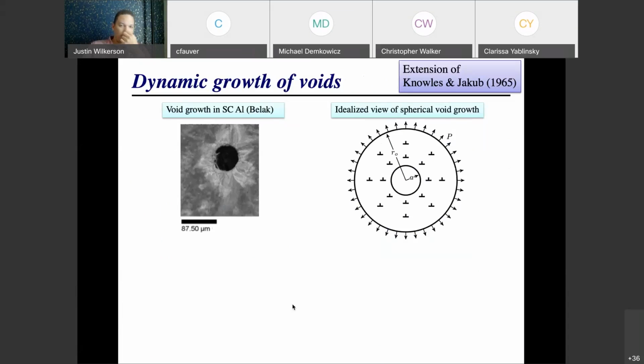Okay, so last defect I'm going to talk about as far as kinetics go is the kinetics of voids. So the question is, we've talked about how fast cracks grow, how fast dislocations propagate, how fast twin boundaries move, and now we'll talk about voids, how fast voids grow. So again, there's going to be this linkage to the kinetics of dislocations, because as I mentioned earlier, the way the void grows is by plastic deformation of the surrounding matrix material around the void.